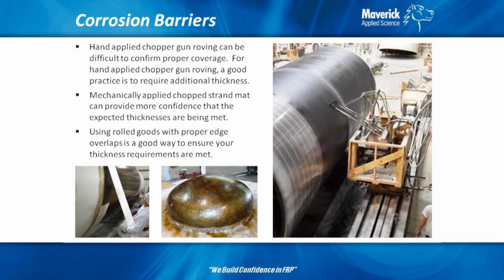So if you use the hand chopper gun on this part here, you would probably get good effective coverage and you wouldn't have a lot of extra double overlaps like in the center. Typically though, if you want to make sure that your corrosion barrier has the right thickness, has everything you ask for, if you use rolled goods with a proper overlap, 1.5 to 2 inches of overlap on your edges, you'll get the thickness that you're expecting. So that's an easy way to verify that you are getting what you want.